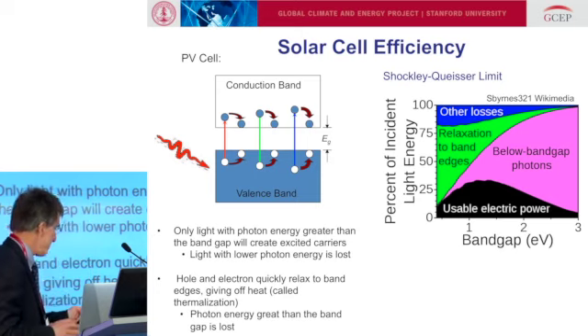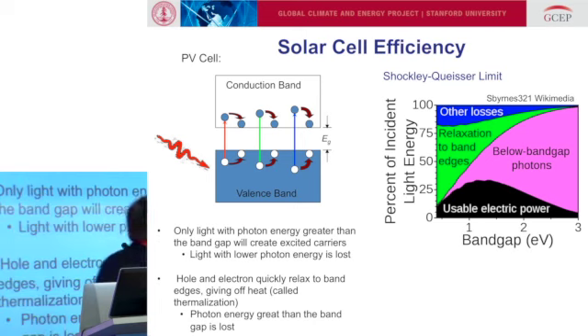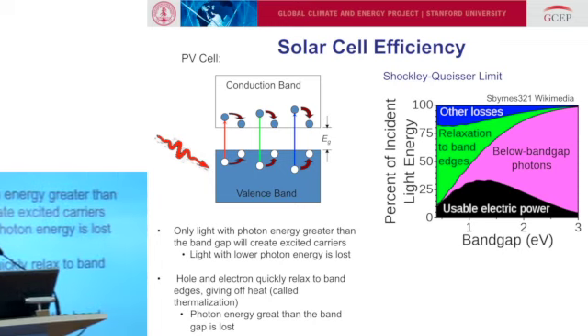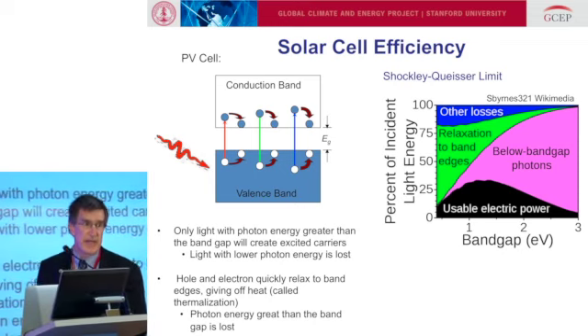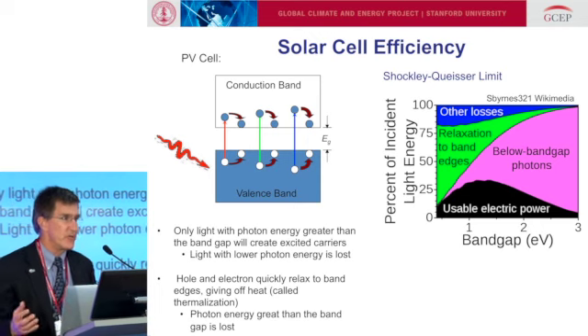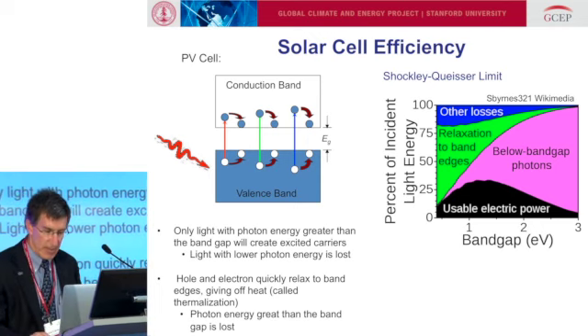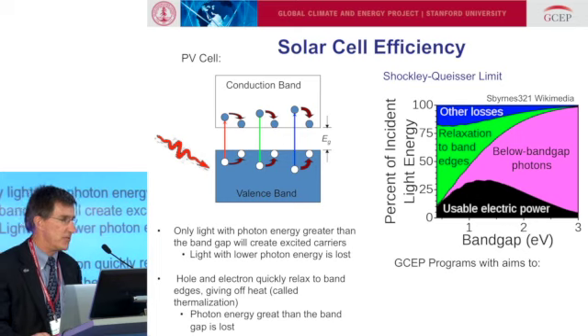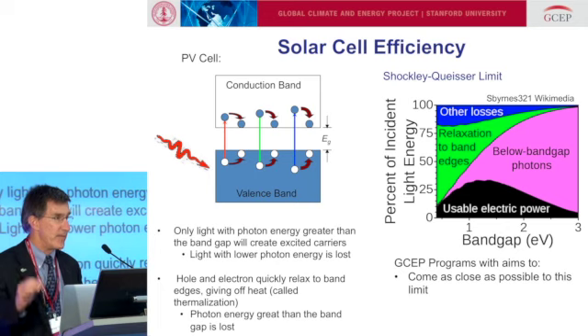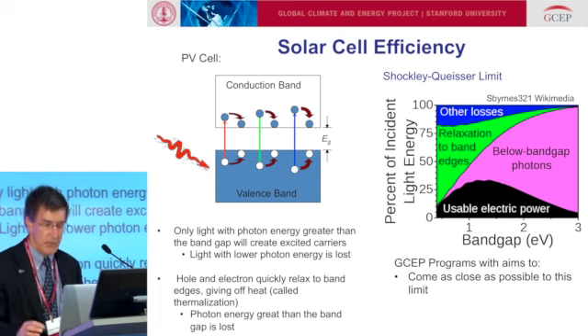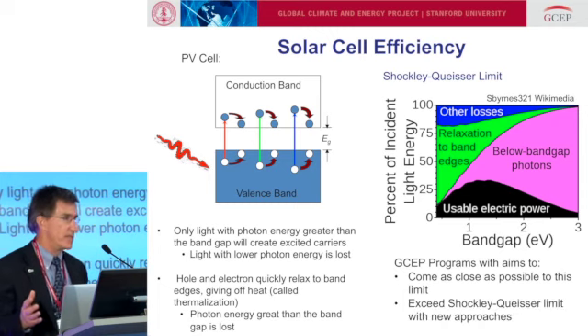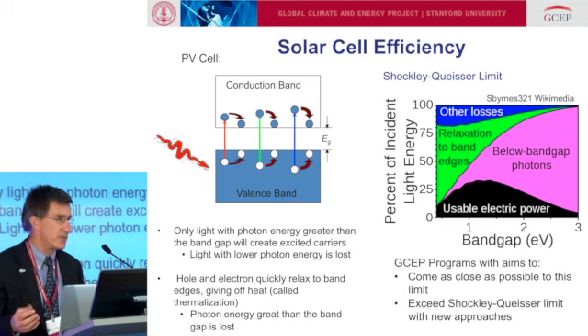Here it is plotted as a function of the band gap, and you can see it peaks at a band gap of about 1.4 eV, and it peaks at about 30-something percent. So that's as good as you can ever do with a single junction solar cell. There are two approaches that GCEP is using to try to get high efficiency: one is to come as close as possible to that theoretical value in inexpensive solar cells, and the other is to exceed this limit by trying new approaches that aren't just single junction solar cells.